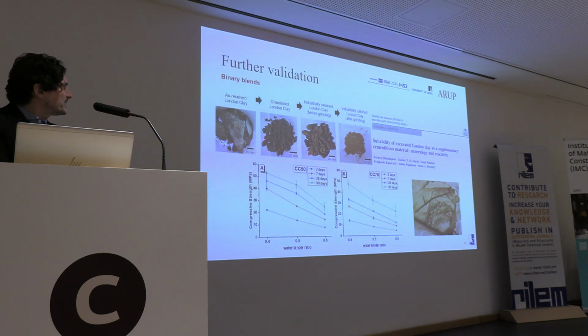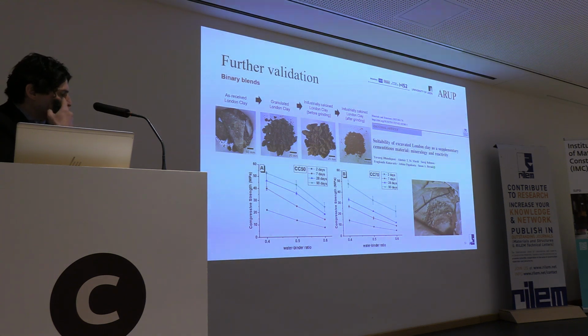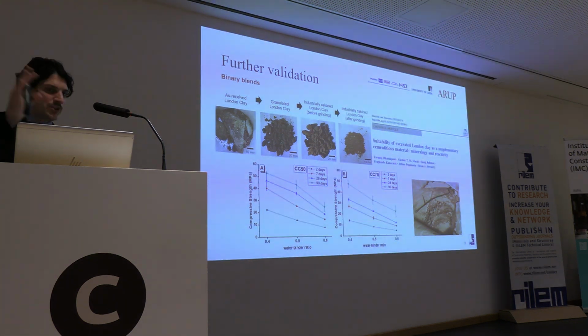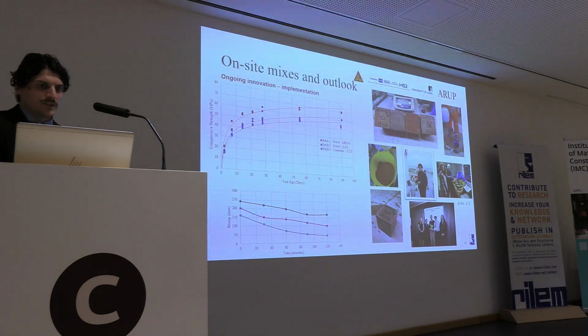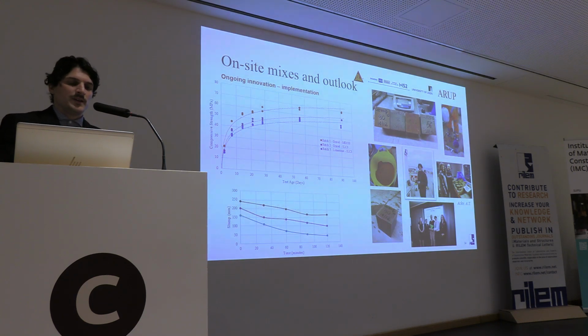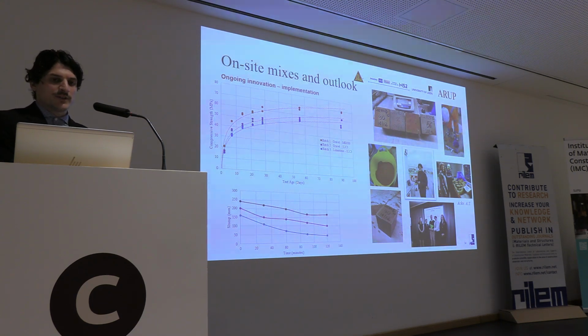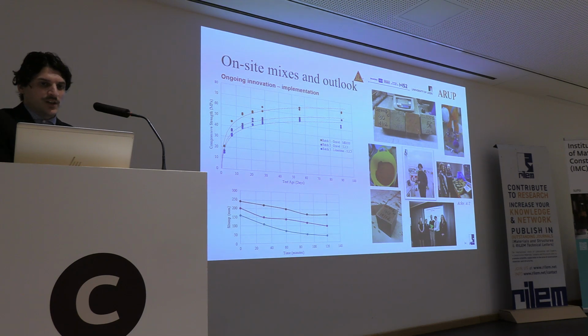Here you can see the process from as-received clay all the way to the powder that was eventually used. This is a sample from the site. And even going up to 70%, you can see that we can produce 40 megapascal strength approximately, depending on the water-cement ratio, which is really pushing it to the limit. And that was really confirmed from site mixes that were developed and tested in the laboratories of the contractor, which is SES JV.